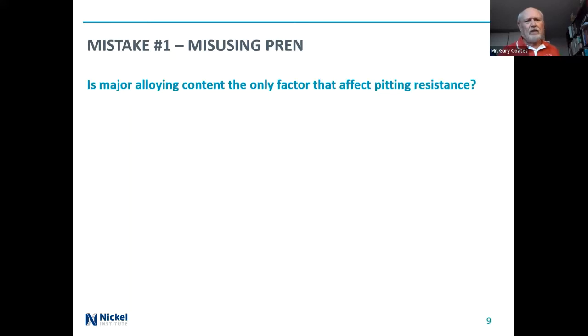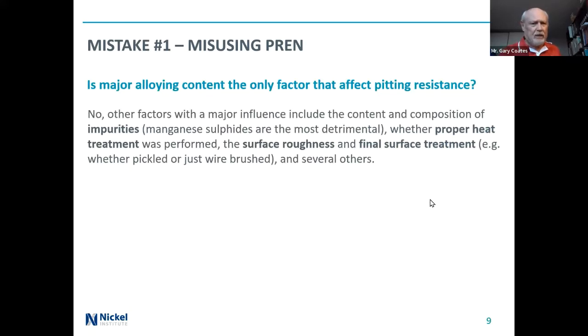So are the major alloying elements the only factor that affect pitting resistance? Well, the answer is no. There are many other factors that have major influence on the pitting resistance, and one of them is the content and composition of impurities, and manganese sulfides are the most detrimental. Today, many steel producers have a refining system that will reduce the sulfur down to 0.001%, very, very low compared to what it was before. But not all producers have that ability, and manganese is always in stainless steels as a deoxidizer. So when you have a higher sulfur content, you also have manganese sulfides present, which are very detrimental for pitting resistance. Proper heat treatment can be very important.